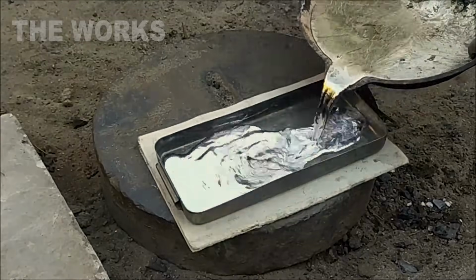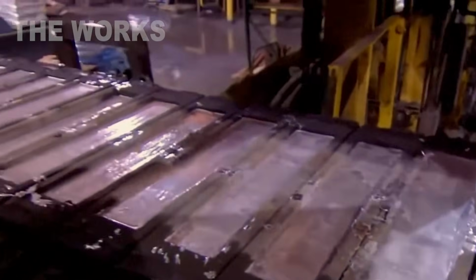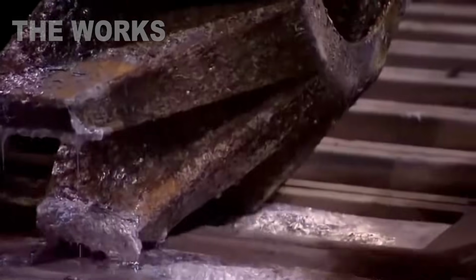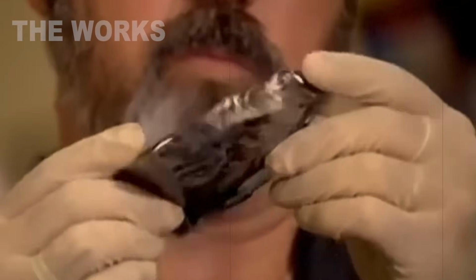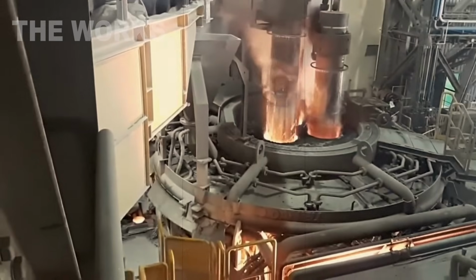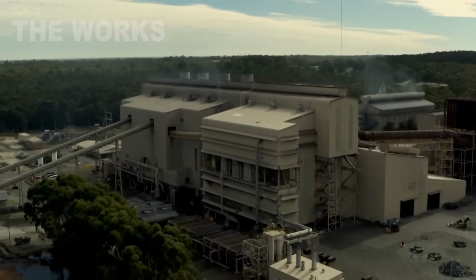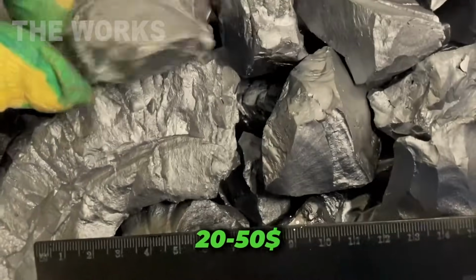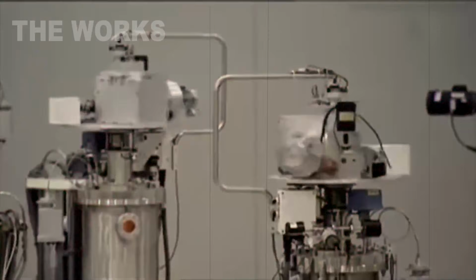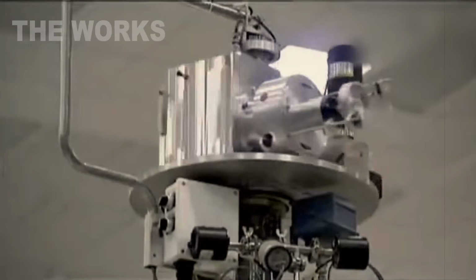In that time, those thin rods grow into thick cylinders up to 8 inches in diameter and weighing up to 660 pounds. They look like giant gray icicles. This is polycrystalline silicon, the purest material humans have ever made. Purity reaches 11 nines, 99.999999999%. A single kilogram of this silicon costs anywhere from $20 to $50, tens of times more expensive than metallurgical grade. The polycrystalline silicon gets chopped into chunks and shipped off to single crystal manufacturing plants.